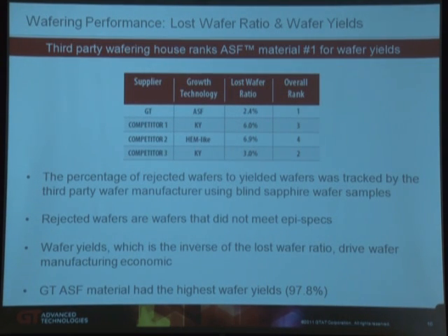One of the critical economic criteria for a wafering house is yield. Simply, that's the amount of millimeters of core or millimeters of sapphire material to start with. How many good wafers do you get at the end? And so one of the criteria that we used was to have the wafer house supply us with the yield of the cores through their whole process. And the percentage of rejected wafers to yielded wafers was tracked by the third-party wafer manufacturer using blind sapphire wafer samples. In this case, again, using the average yield, the ASF material had the highest wafer yields at 97.8.